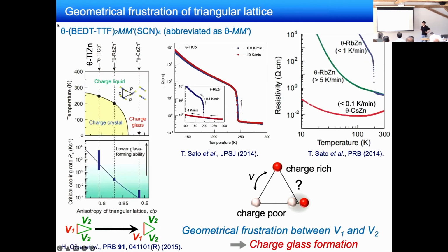And it is well known that the charge ordering temperature and the critical cooling rate for the charge glass formation can be controlled by the anisotropy of the triangular lattice, V1 versus V2. It is also well known that the geometrical frustration between V1 and V2 plays an important role for the charge glass formation in this system.